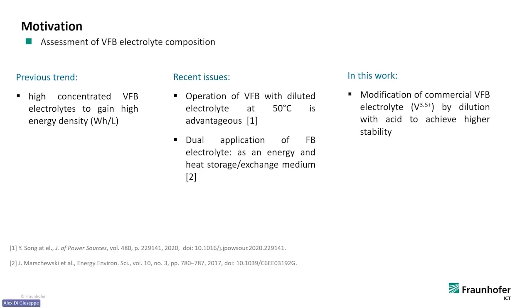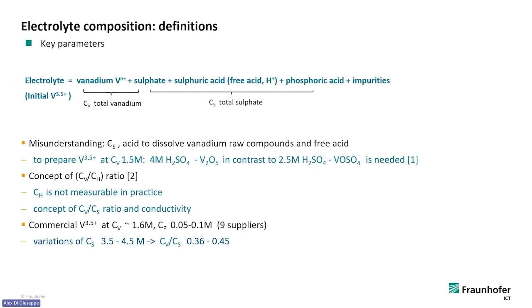As I said, usually you want to increase energy density. For this project, we said, well, let's go the other way, maybe dilute the electrolyte so that it gets more stable for higher temperatures. Especially we know that acid content has a big influence on stability. We said, let's dilute it, put more acid inside, then we can maybe gain some stability. So dilution was the issue here, what we wanted to achieve. And of course, we wanted a compromise, so that we have enough energy available to run the battery operation, but still be able to support higher temperature levels.